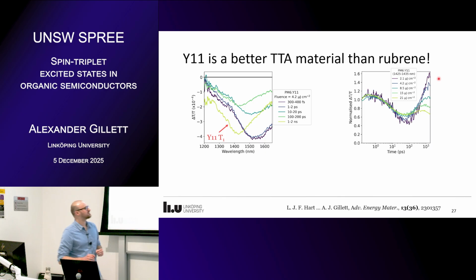And it almost looks like the low fluence is forming more triplets than the higher fluence. Like you see, as we increase the fluence, this peak gets relatively less intense. And that was really, really weird. Then we thought about it a bit. And if you look at this little bit here, you can see actually, at least at the start, you get the trend you expect, which is lower fluence has a less intense triplet peak, and then higher fluence gets more. So that was kind of strange.